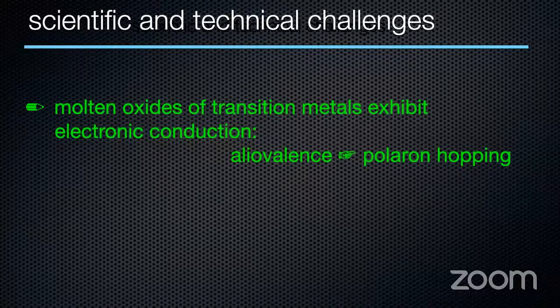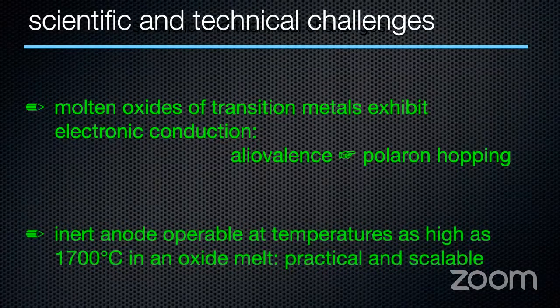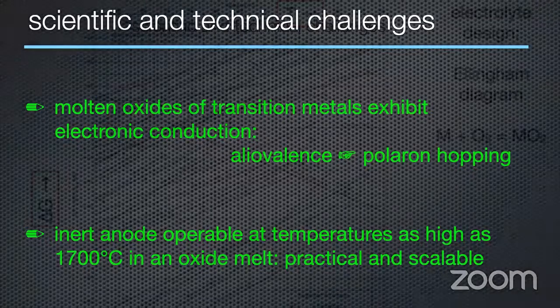And it was just cook and look. I mean, molten oxides of transition metals, they exhibit electronic conductivity. That means your Faradaic efficiency is going to be crummy. So we had a lot of challenges to tailor the oxide solvent. And then, of course, an inert anode. What are you going to make of it? You need something that can resist oxygen and be immersed in a molten oxide solvent and operate at 1600, 1700 degrees C. That was our big challenge. So put all those together and then finally you can do this.